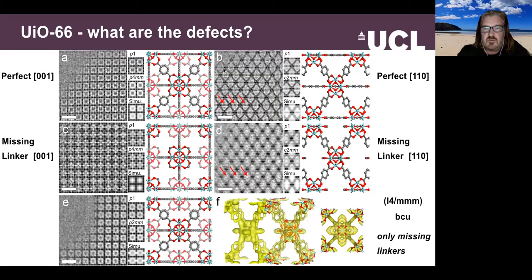So what I want to draw your attention to is this particular figure. This is the unit cell of UiO-66, which has been rotated, so looking along a particular plane. And you can see here that along here we have flat phenyl rings. And these actually map onto these struts, which you can see highlighted in this TEM image.